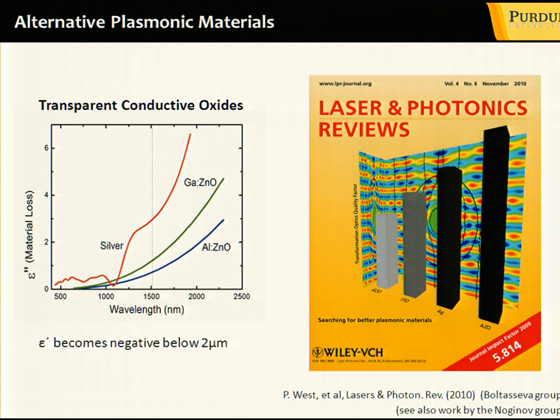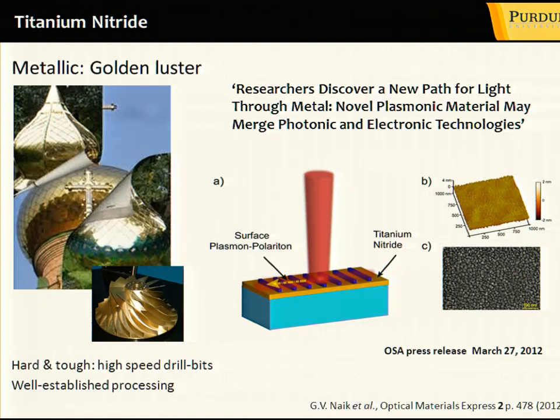Here is an example from the Boltasseva group where they show that these highly doped transparent conducting oxides, such as gallium doped zinc oxide and aluminum doped zinc oxide, where epsilon prime becomes negative below 2 microns, so close to telecommunication wavelengths, have an imaginary part that could be smaller by a factor of 3 to 5 than in silver, and silver is considered to be the material of choice. So you could see that epsilon could be negative, not necessarily minus 100, which sometimes actually is a problem, at least for some applications. And the imaginary part could be smaller. This is an example of how you could really engineer plasmonic materials with desired properties.